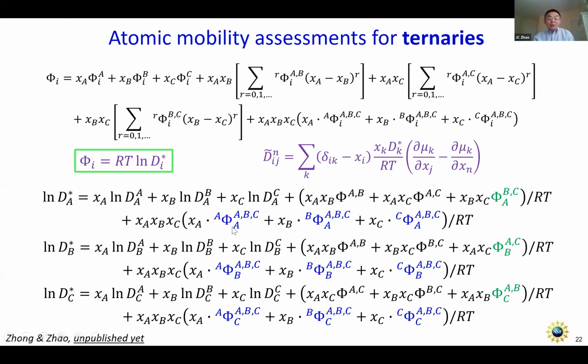And then you got 3 ternary interaction parameters for A. The same thing, you get B and C. So basically you can see there are 3 cross binary terms, and then there are 9 ternary terms. You get 12 terms to fit, right? So that's a lot of parameters, and usually in a lot of the binary ternary systems, we have very few data points to fit. So if we fit 12 parameters, that's way overfitting, right?